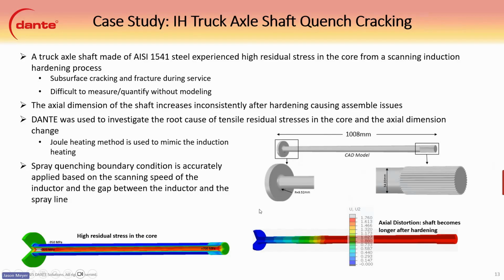And so we used a Joule heating method to mimic the induction heating, kind of mapping the temperature profile from the modeling. Since we don't really model the electromagnetics, the Joule heating works really well for this process. On the outside, there was a spray quenching boundary condition, and that is applied to the scanning speed of the inductor. And then the gap between the inductor and the spray line was used to model this.